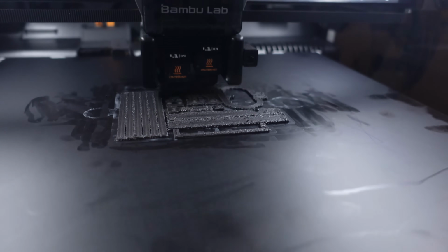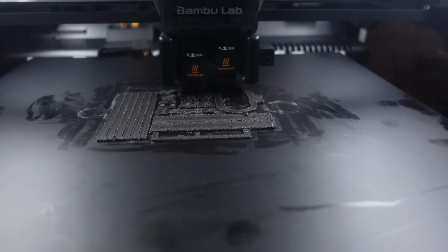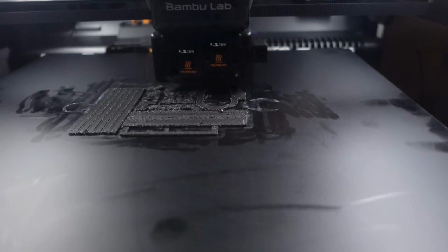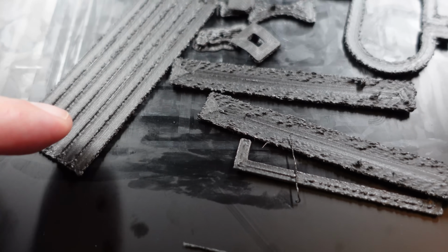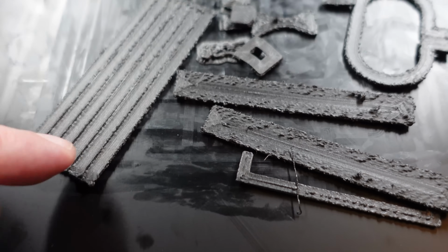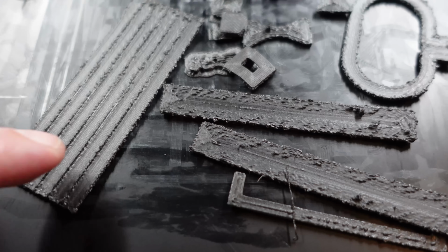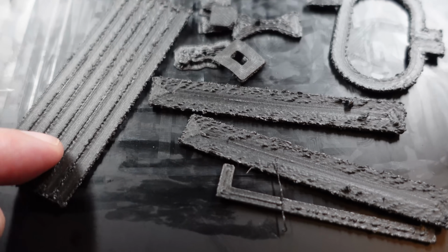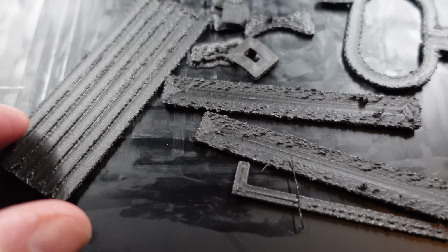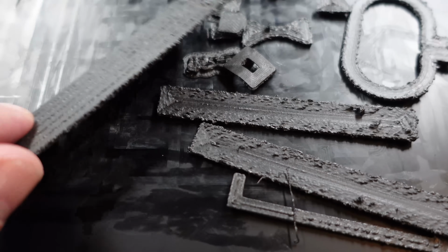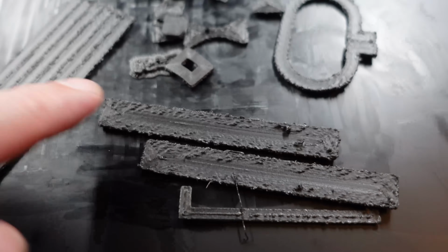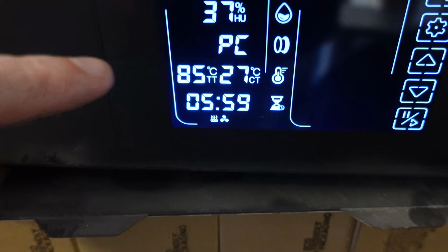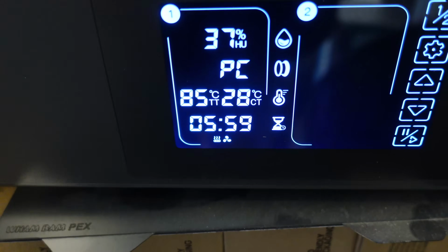Well, I will stop this printing because it needs some drying. H2 printers are more sensitive to this kind of moisture, and I have the feeling if I would print this on X1 Carbon, it would be fine, but I don't have an actively heated chamber, so I will dry the filament and reprint the test objects. And the drying: 85 degrees Celsius, 6 hours. I saw this so many times with H2 printers. They are more sensitive to moisture.